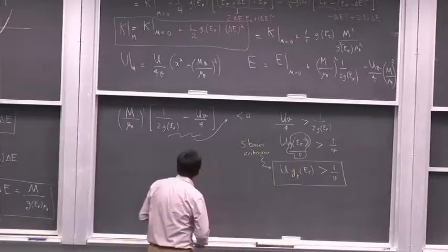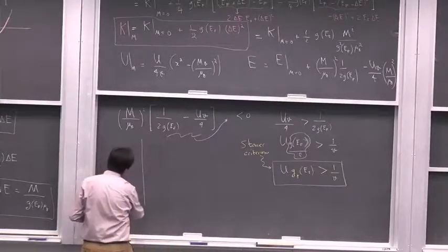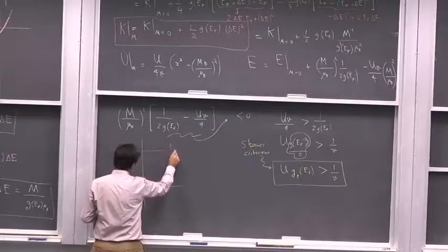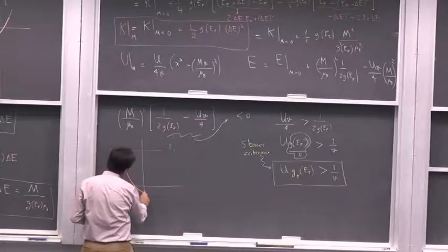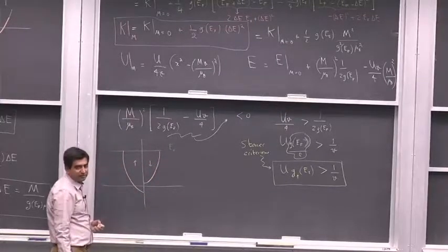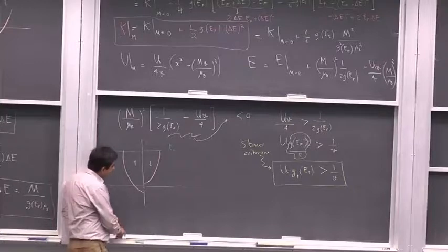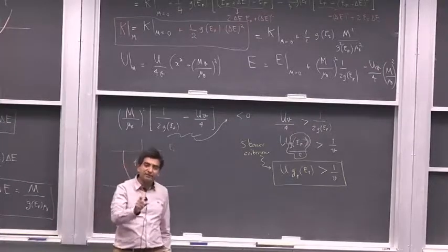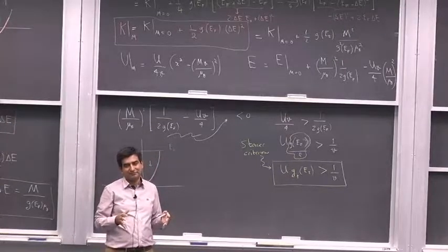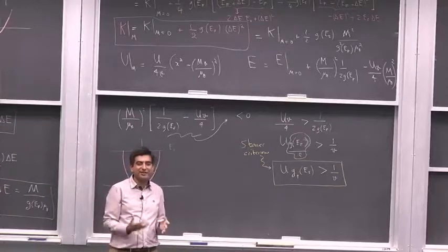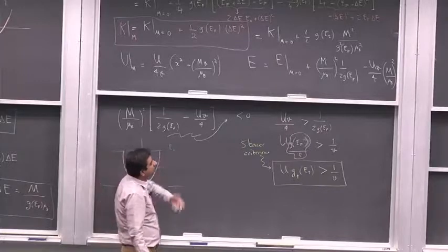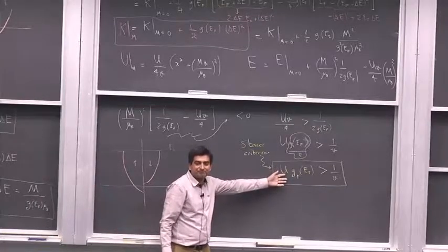And if the sample would like to magnetize spontaneously, it means that if I draw the Fermi level, EF, there will be more spins of one kind and less spins of the other kind. There will be more majority spins and less minority spins. So the sample will become spontaneously magnetized. And this splitting is now not due to an external field, it is due to interactions between the electrons. Sometimes it's dubbed the exchange interaction. So this is mediated by an exchange interaction. This exchange interaction is modeled through this Hubbard interaction.